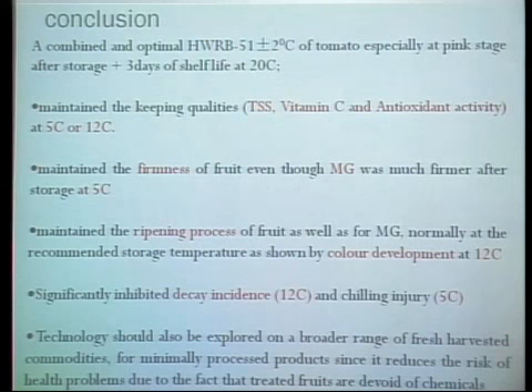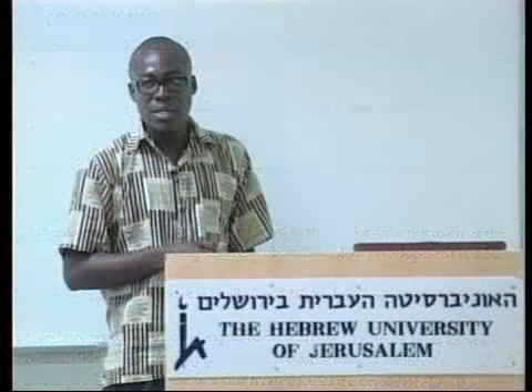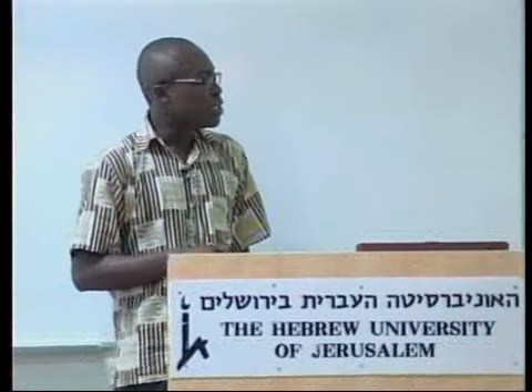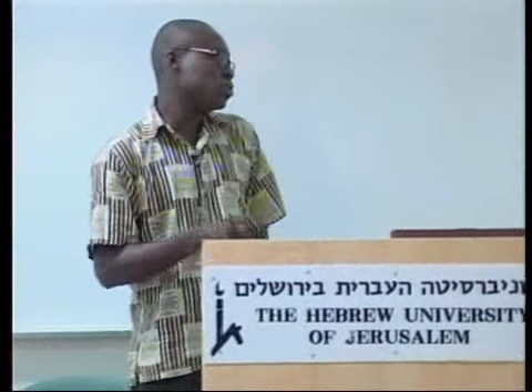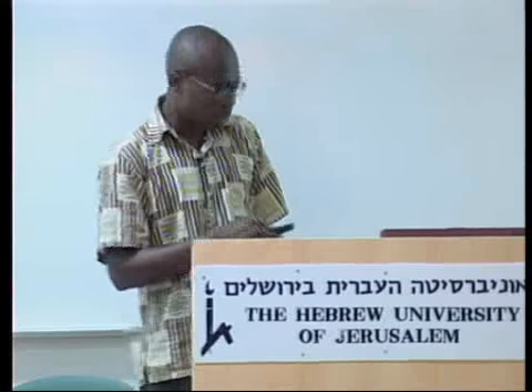for minimally processed products, since it reduces the risk of health problems due to the fact that the treated fruits are devoid of chemicals. Because as you can see in this treatment, we didn't use any chemicals. We only used water to wash the fruit. So we think that it should be explored not only in tomatoes but in other commodities.